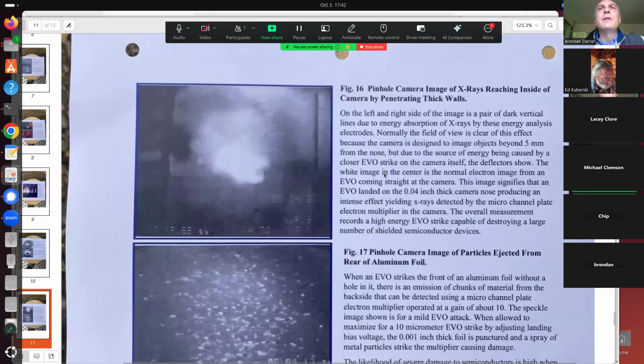The white image in the center is the normal electron image from an EVO coming straight at the camera. This image signifies that an EVO landed on the 0.04 inch thick camera nose, producing an intense effect, yielding X-rays detected by the micro-channel plate electron multiplier in the camera. The overall measurement records a high-energy EVO strike capable of destroying a large number of shielded semiconductor devices.